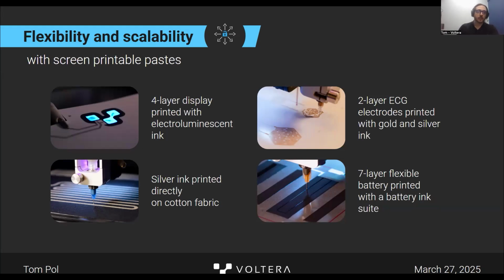And just for a couple of examples I've listed here, we have done a 4-layer electroluminescent display using a blue phosphor ink, biocompatible EKG dry electrodes printed with gold, stretchable silver ink that we've printed directly onto fabric to make some heated up mittens for our frigid Canadian winters, and a printed battery, which consisted of 7 layers and a variety of different materials.